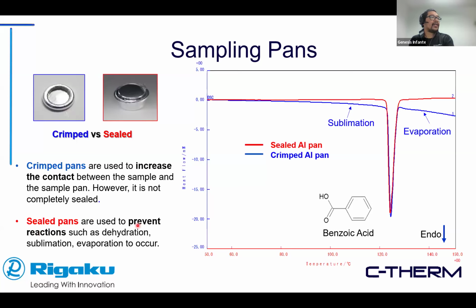But in terms of sealing it, you want to prevent dehydration or loss of mass during your reaction. So for example, right here we can see there's a benzoic acid test. There's two tests, identical amounts, identical heating rate and whatnot. But for crimp pans or aluminum pans, it's not completely sealed. So during sublimation, you can see that there is a shift on the baseline because you're losing mass as it goes, and that shift increases at higher temperature due to evaporation of your material. So again, you get similar data or similar intensity, but you got this error right here that needs to be accounted for, so you probably want to make sure that you're doing the best possible condition in terms of sample prep.